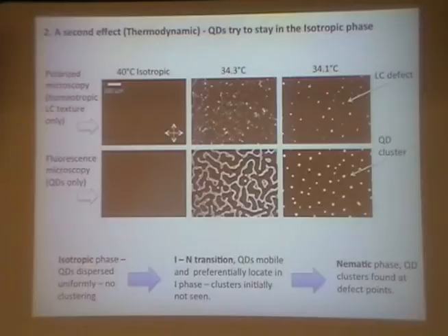if possible. So here we can see two series of a material that contains quantum dots, going to cool through the transition into the nematic phase. The top row here is just the birefringence, and we're in a homeotropic cell, so we're not going to see a lot. In the bottom row here, we're only looking at quantum dots. That's the emission. So we can see when we start in the isotropic phase, things are uniformly dispersed. It's a bit dark, but what we should see here is that quantum dots are uniform in the isotropic phase. Then as I cool through the transition, in the birefringence we can see the nematic phase is coming in, but we leave behind islands of isotropic.